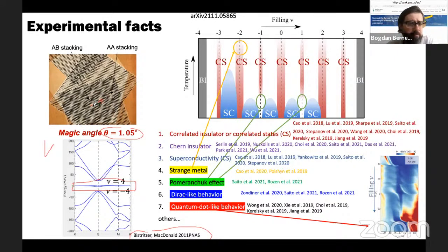The Brillouin zone is much smaller. And in this Brillouin zone, you get a series of bands that are very flat. Now, you get also some dispersive bands, and the velocity of these dispersive bands is basically that of the Dirac fermions of the original graphene. But the appearance of these very, very flat bands leads to interesting consequences. The consequences are the following. First, we have to count how many electrons we can put in these bands. Now, it turns out, for reasons that I'll explain in a little bit, that there are several symmetries in this problem. First of all, there's a spin symmetry, which leads to the factor of 2. Then there's a valley symmetry, which leads to another factor of 2. And then there's 2 bands, because like in graphene, I have Dirac fermions, even at the moire K vectors. So this is all these are moire vectors. So there's another 2 bands. So in total, there's 8 bands separated in quantum numbers that we'll explain in a little bit.